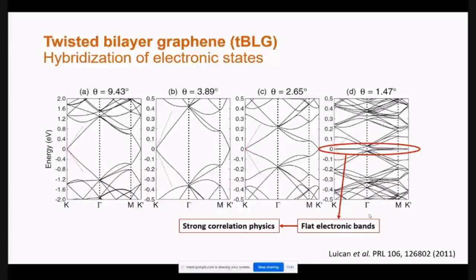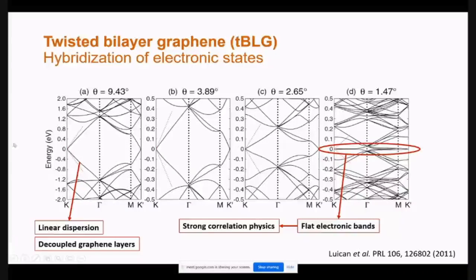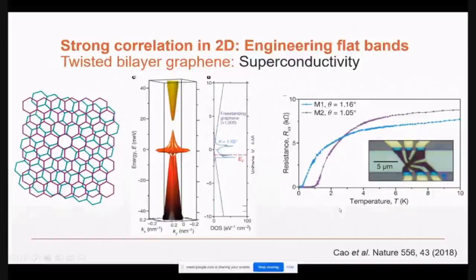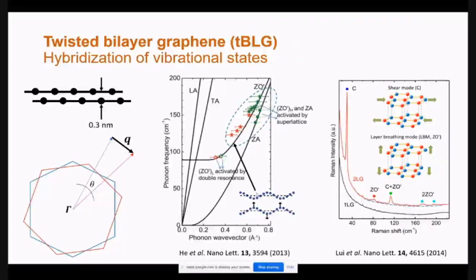This has been one of the latest kids on the block in terms of craze and activity, in terms of new phenomena that have been shown. However, here essentially there is supposed to be no coupling between the two layers. At around 1.1 degrees, superconductivity, because of strong correlation, has been claimed, although it is still a very open question whether the superconductivity is really a strong correlation effect or not, or at least how much role the correlation plays in the observation of superconductivity. It is a matter of completely open debate, even after more than 2 years of publication. But it turns out that electronic hybridization is not the only hybridization.